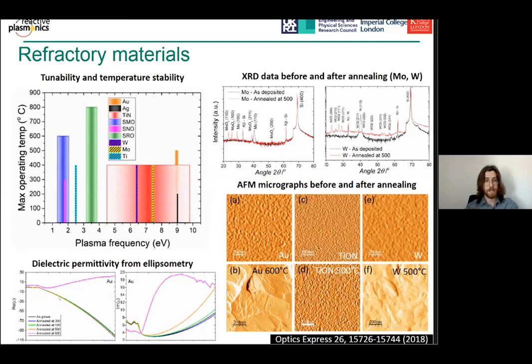And we were waiting to see if there was any significant change in the optical response, in the structural response, or in the surface morphology. And we found that the degradation mechanism for these materials differed depending on the material platform that we were using. For example, gold's response changed dramatically because of surface morphology changes, whereas with titanium nitride and titanium oxynitride, there was little change in the surface morphology, but we did see change in the optical response due to oxidation of the films. And if we look at the refractory metals, for example, tungsten, this is a combination of the two. So we see oxidation of the films and changes in the surface morphology. But as I say, this allowed us to identify which material could practically be used in different applications.